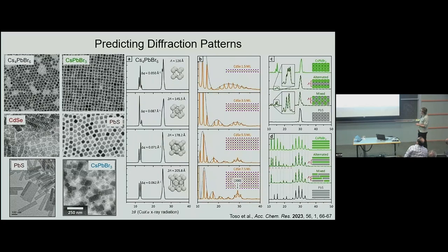Here's a case for different thicknesses of cadmium selenide nanoplatelets in a zinc blende crystal structure. We tried, but we couldn't get nice assemblies, probably because these platelets are quite flexible and susceptible to different twists and distortions.